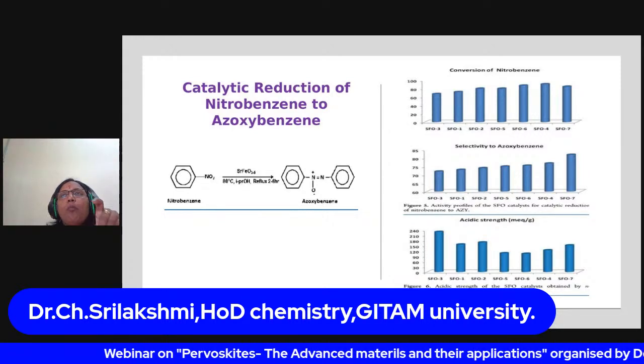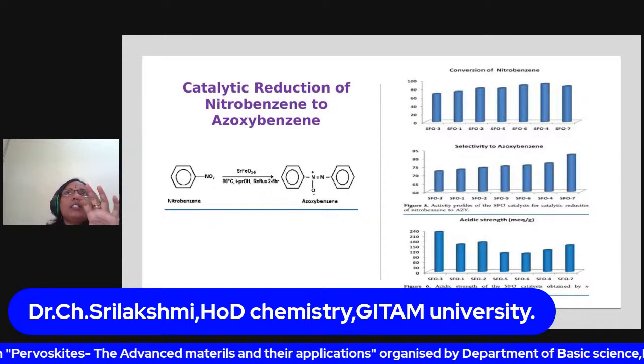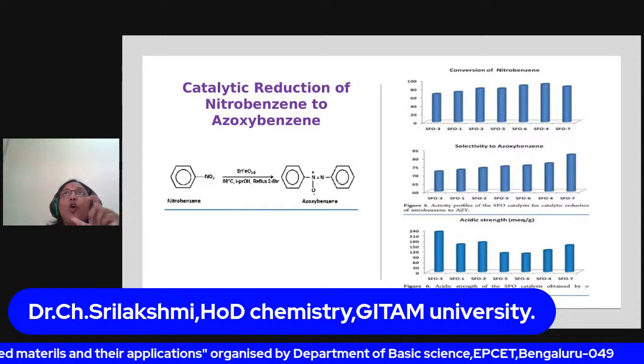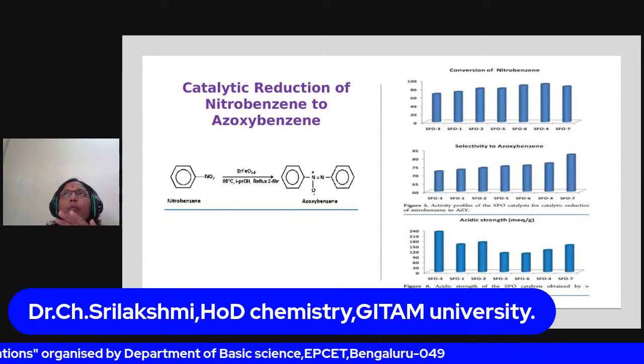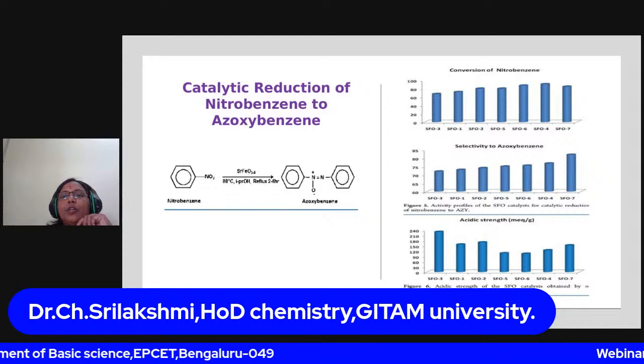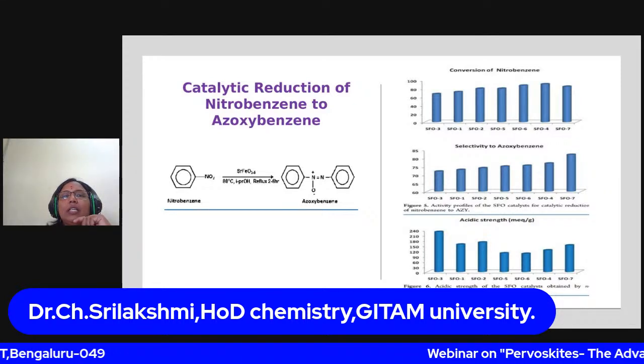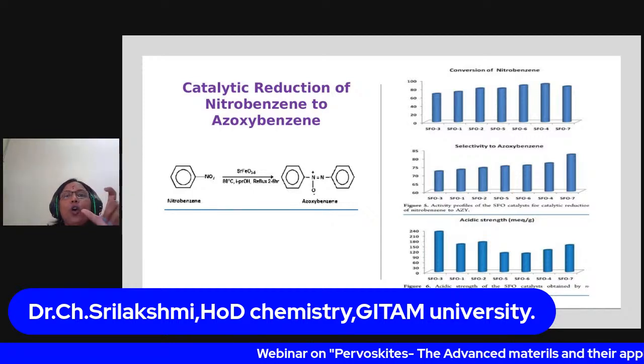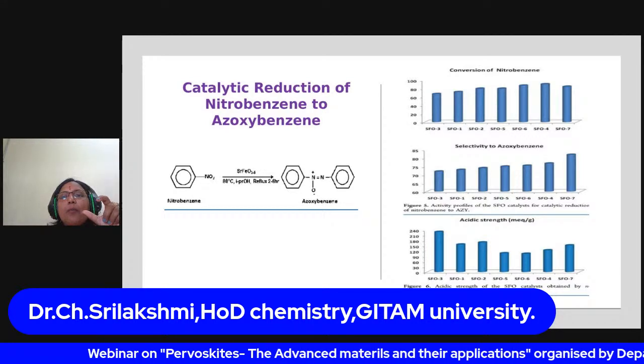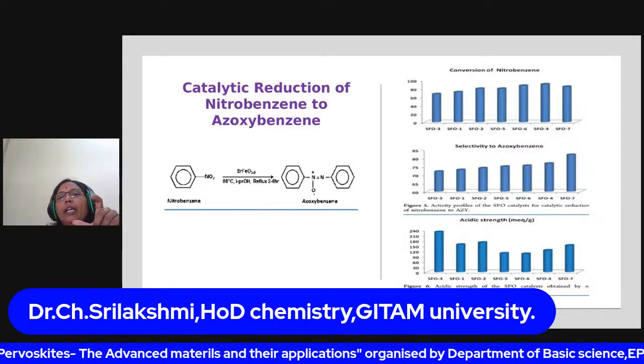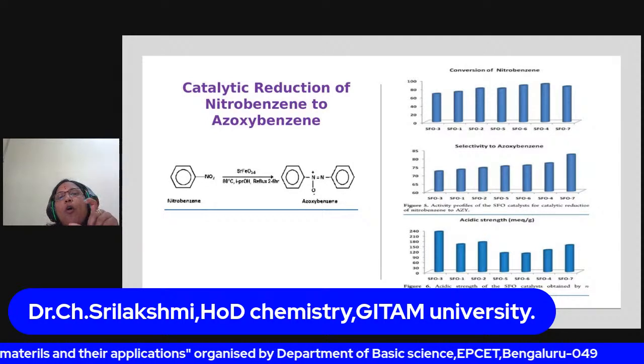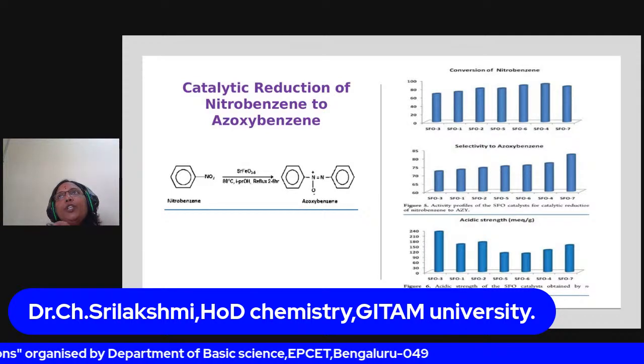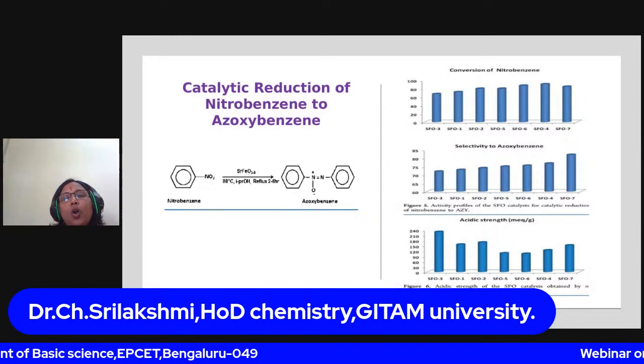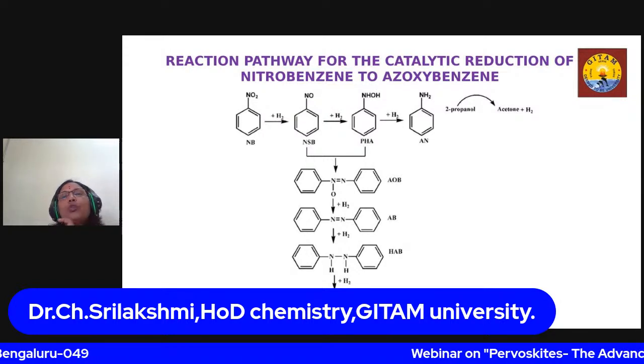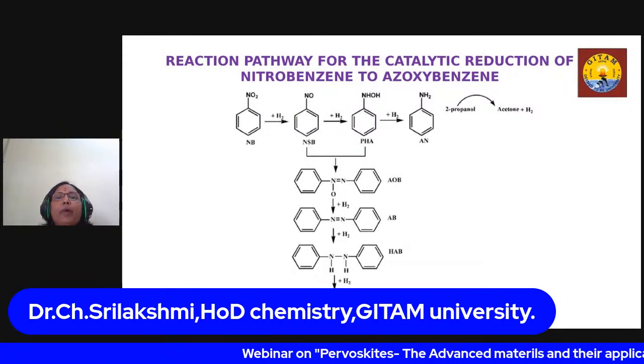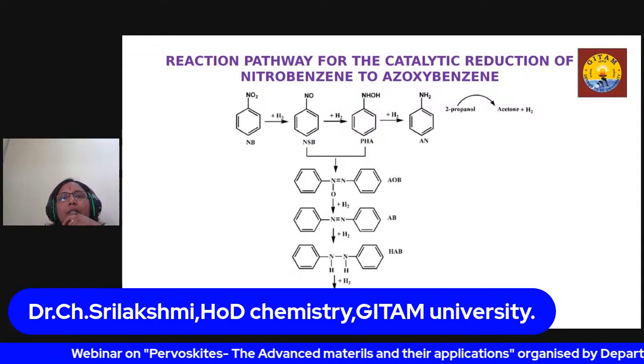It means that in order to form azoxybenzene selectively, the redox nature of the catalyst is essential. Redox nature of the catalyst means it should not be too acidic, nor too little, it should be moderately acidic. That increases the azoxybenzene. That's the reason we got azoxybenzene instead of aniline, because in these samples what we observed is that aniline formation is more. So in order to selectively form azoxybenzene, we definitely need moderate acidic strength, but not high acidic strength. So we came up with a new reaction pathway. Then the reviewer asked, can you propose the reaction pathway?